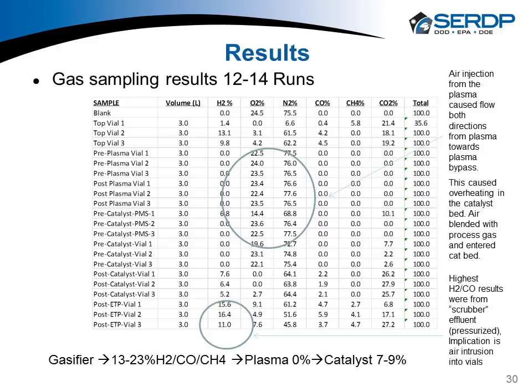After the plasma, we saw 0 again because of the operator error I think we had going on, and then we blended that basically pure air stream with the bypass of the plasma. That went into the catalyst bed and then came out at about 7 to 9% hydrogen, carbon monoxide, and methane.